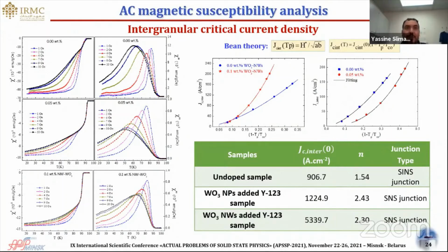To validate this evidence, we calculated from these curves the intergranular critical current density of samples by means of the Bean model. Here it is found that the intergranular current density improved with tungsten oxide nano entities addition. For example, tungsten oxide nanowires showed the best intergranular critical current density values, and the improvement compared to the pristine compound is about 2 to 5 times.